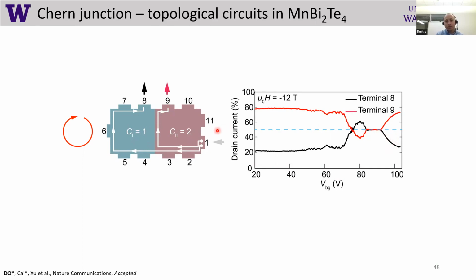When we perform this measurement, sending current from here and detecting it here and here, what we find is there is a region outlined in yellow, as a function of backgate voltage, when the current splits perfectly 50-50%. So essentially we send current, then there is what you can call a beam splitting event, when one edge state moves here, one moves here. And I will draw your attention to the fact that these edge states could have a different length, but indeed the splitting would be 50-50 because these states are topological. So independently of the length, the resistance would be the same.